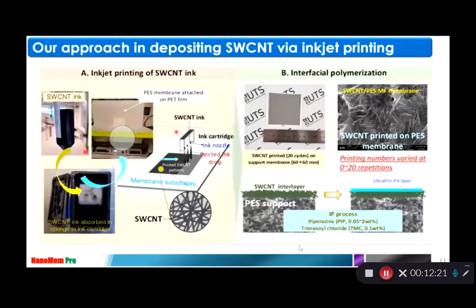So this is the inkjet printing. We purchased one inkjet printer from a commercial supplier, and this is the cartridge. We mixed our ink into the cartridge, installed it in the printer, and tried to print our SWCNT and see how it performs. So this is our membrane sample. You can see it on top of the PES MF membrane. We utilize our SWCNT interlayer, and then we try to compare how this improved the overall ultra-thin polyamide. 10 nanometers was our target, but in fact our experimental data was not really able to create 10 nanometers, but very close. And then I want to share the next slide.